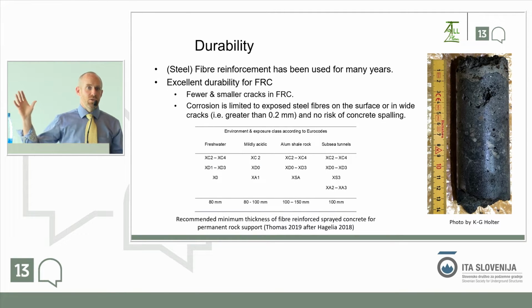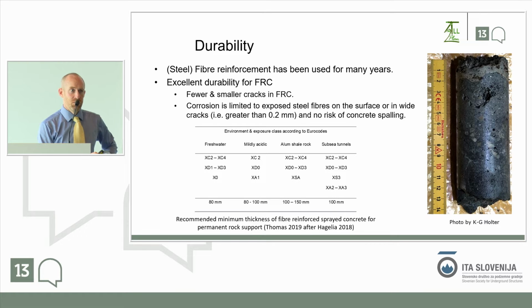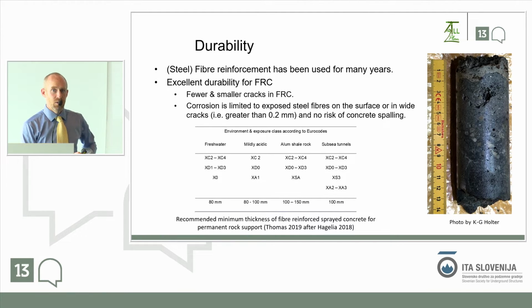Durability, to cut a very long story short, fibre-reinforced concrete of all types is much more durable than bar reinforcement. We know what the problems are with reinforcing concrete with steel, and the attack is very often related to the steel rather than to the concrete itself. So if we assume we can solve the durability of the concrete, if we use fibres, we have inherently a more durable material. We can use fibres that don't corrode, basalt, macrosynthetic, for example. If you have a steel fibre in an open crack with water, oxygen, that steel fibre in the crack will corrode, but the rest of the fibre is embedded in the concrete. The fibres where the crack is very narrow won't corrode.